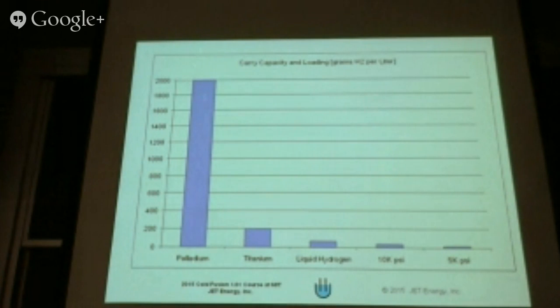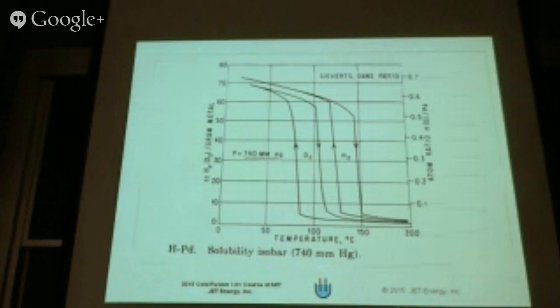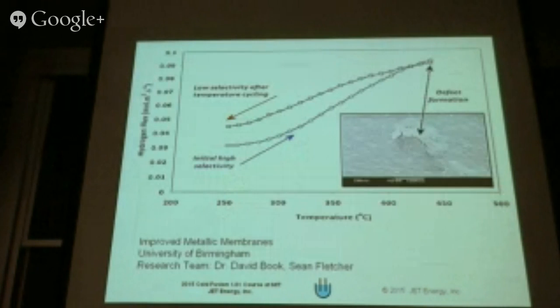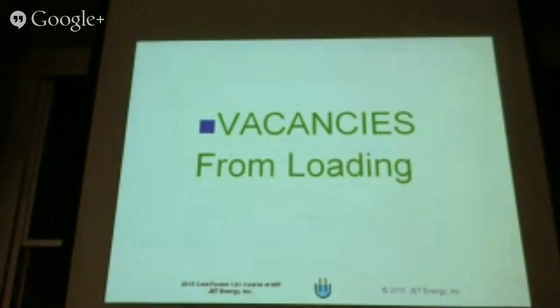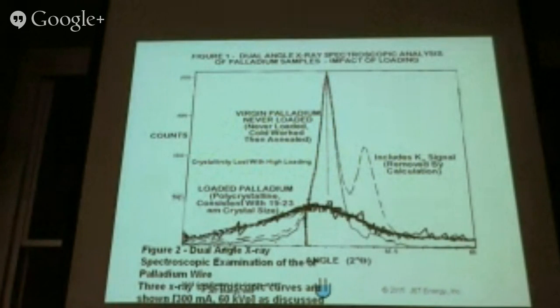And palladium stands out in terms of its carrying capacity, higher than most other metals. It turns out that I am a real believer that although you want vacancies, you don't want cracks. I do not find excess heat from cracks. I know there are people on the internet now saying cracks are the secret ingredient. I think they're smoking it unless they can come up with some evidence. Anyway, when we load, we destroy the palladium. Peter and I took these X-ray spectra years ago. Here's the palladium before loading, and we get back cracks after loading.